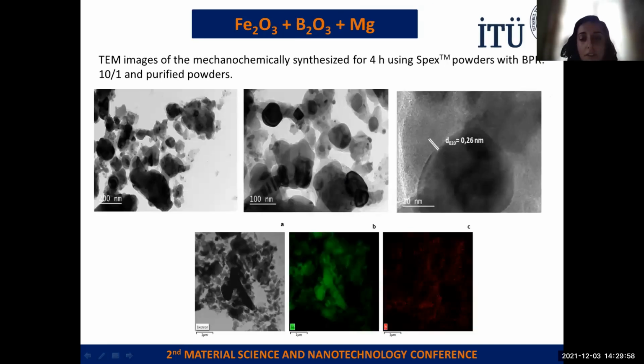And also these are the transmission electron microscope images, and still after the leaching, we can see the iron and boron phases in the elemental mapping structures located at the same place, and there are no other elements. So the pure iron boride phases were synthesized. Also, we can see the irregular shaped nanoparticles in detail in the transmission electron microscope image.